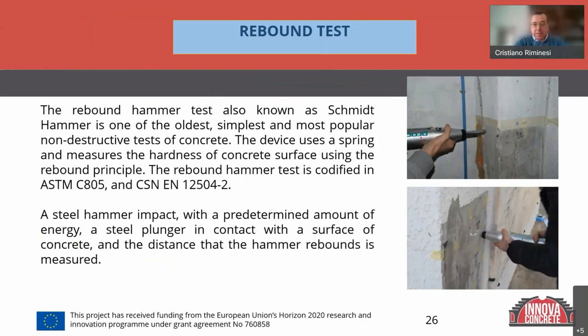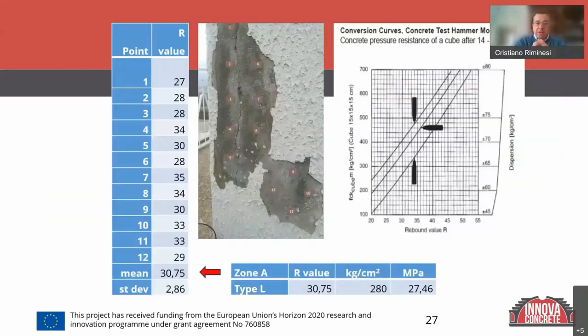Another standard used to understand the hardness of the material is the rebound test by the Schmidt hammer, and this device also complies with the standard. We can measure the energy of the impact of this hammer on the surface of the concrete. Then by this calibration curve, we can convert the rebound value to the strength of the material.